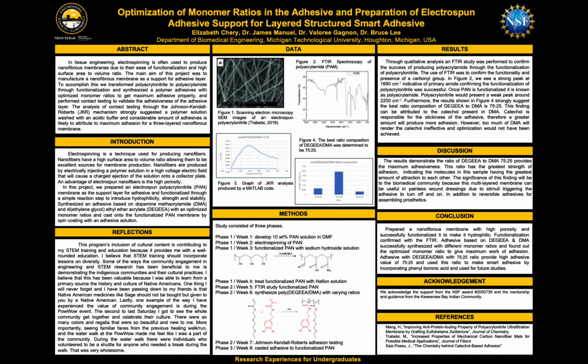And from doing this, I was able to infer that, well, before I say that, I want to say we did this about 9 times. So we had 3 batches, we had 80 to 20, 70 to 30, and 75 to 25. And with each of those, we had tested it dried, washed, and with a buffer of pH 3.0. So we did this 9 times. And after that, I was able to infer that having catechol and acid promotes stronger adhesion.